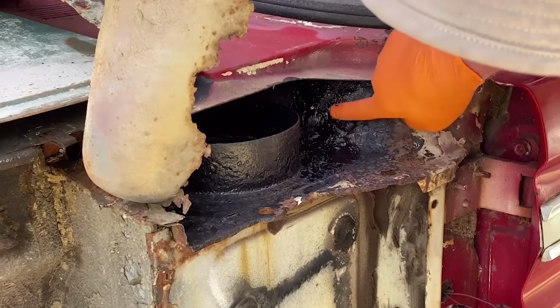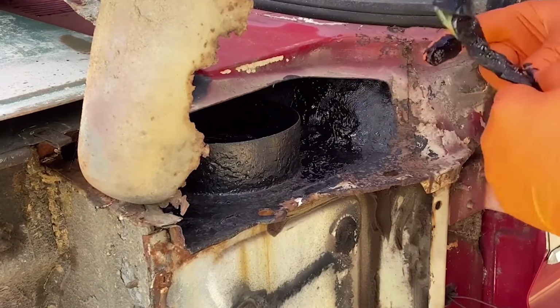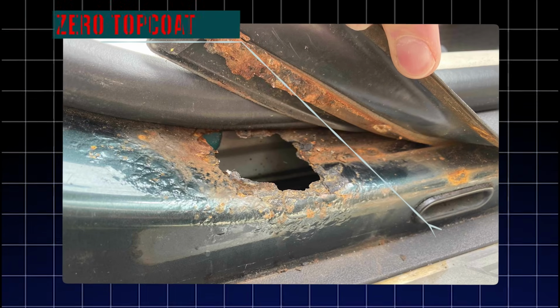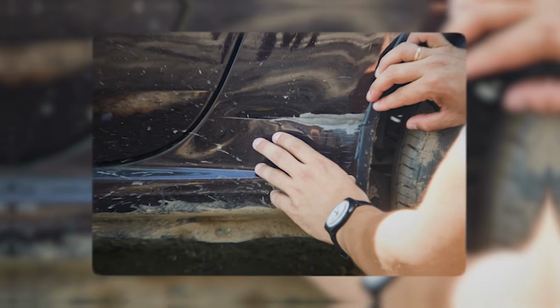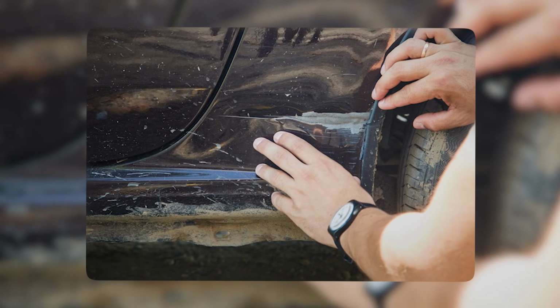At the 6-month assessment point, POR-15 treated test panels on severe rust showed 0 top coat lifting at pit locations, 0 subsurface rust progression visible through the coating, and 0 adhesion failure at the coating edge boundaries.